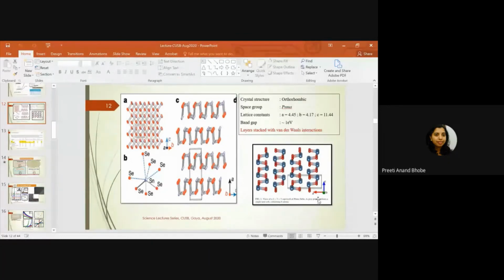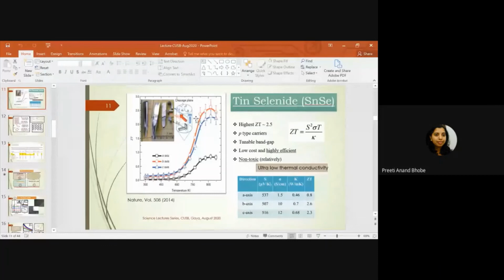Because of such van der Waals interactions which are different along the different axes, whereas in C axis you have a direct chemical bond only, there is no van der Waals interaction there. These are all chemical covalent bonds along C axis. Because of this kind of a bonding, the propagation of phonons that happens along A, along B, and along C are different. And that is the reason the phonons are not being able to propagate through, because phonons propagate through lattice vibration. Now your lattice vibration is getting affected because in between there is a break due to van der Waals interactions, as there is no direct chemical bonding there. So your propagation of phonons gets affected, and that is the reason, as in the previous slide, you have difference in the A, B, and C axis.